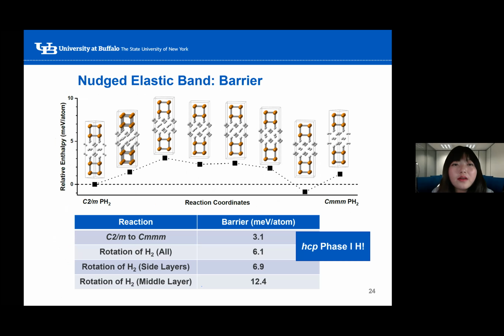So we used the nudged elastic band calculation to estimate the barrier for the reaction pathway connecting the two PH2 phases, and we get a barrier of 3.1 meV per atom. We also calculated the barrier for the pathways of rotating all the molecular hydrogen layers, only the side layers, and only the middle layers in the C2/m PH2 phase. The estimated barriers are all considered low, and therefore we conclude that the molecular hydrogens are freely rotating, and this property resembles that in the HCP phase I hydrogen.